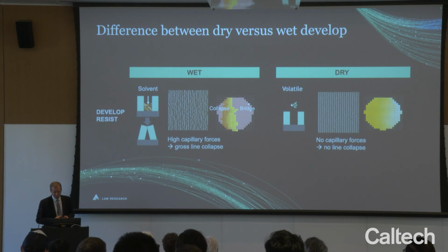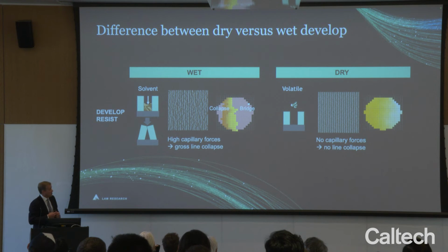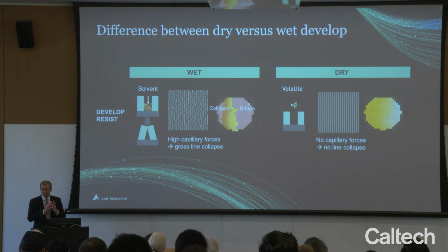And then finally, another benefit of the dry processing can be seen when you think about the development process. After we've exposed the resist, you need to develop it. And that's typically been done by, again, providing wet chemicals onto the wafer. But as features have gotten smaller and smaller, it's very difficult to get wet chemicals in between those features without causing them to collapse due to the capillary forces that exist during wet processing.